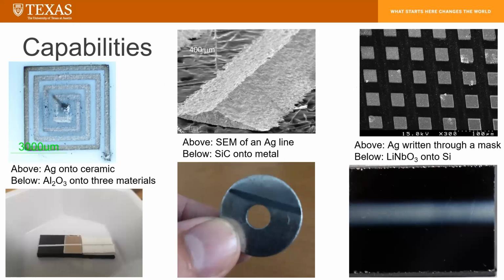So we can actually do really fine feature resolutions using masks. The image on the far right is silver written through a mask. And then after we remove the mask, we can have microscale features. In the bottom, we have ceramics deposited onto things. It is an alumina line in the bottom left, written across ABS plastic, stainless steel, and alumina with one set of conditions.